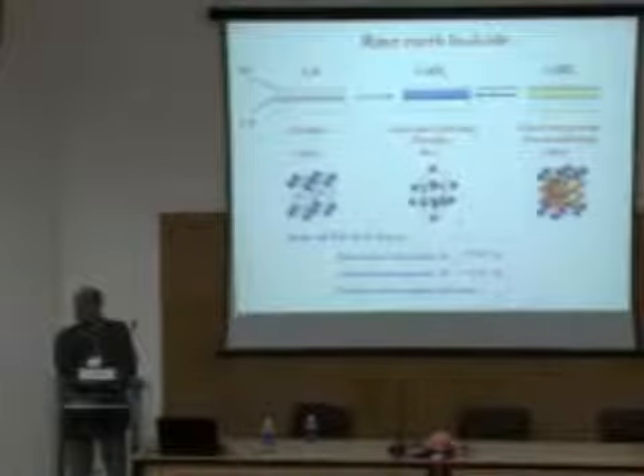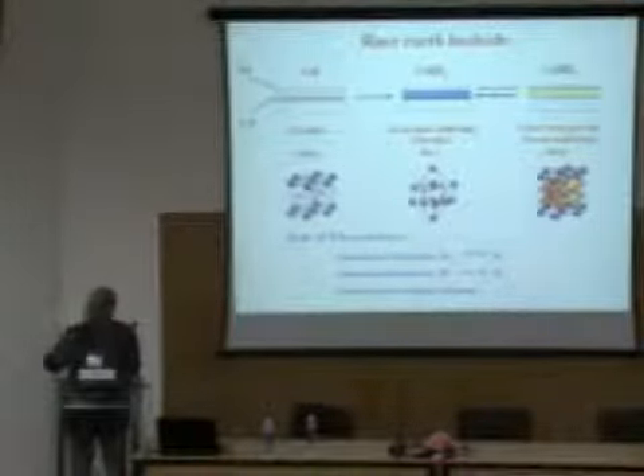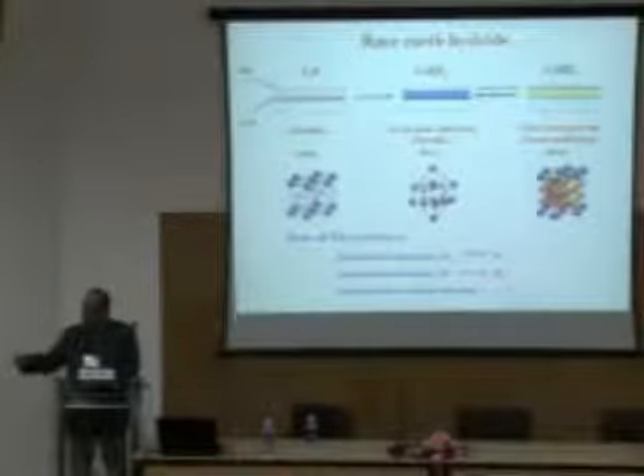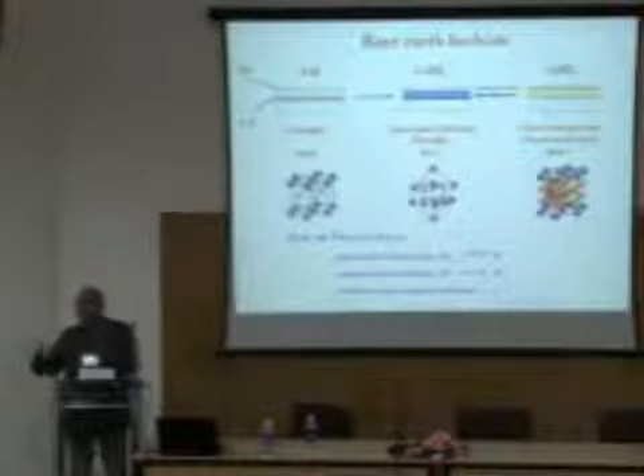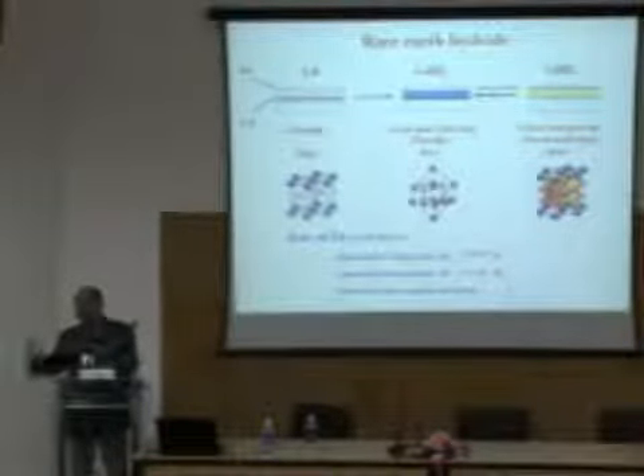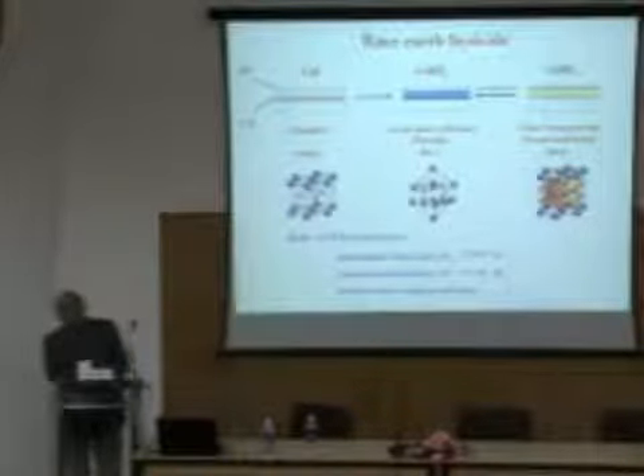In praseodymium, there is no crystal structure transformation. The material remains in FCC structure, but there is a metal to insulator transformation. Optically, the material is changing, electrically, the material is changing, the crystal structure remains the same. So they cannot be related to each other, but they are independently taking place. So it's a very interesting material to study from solid state physics and chemistry point of view.